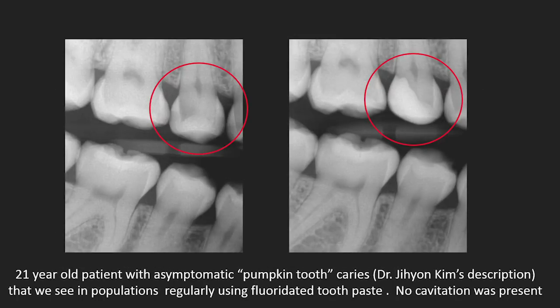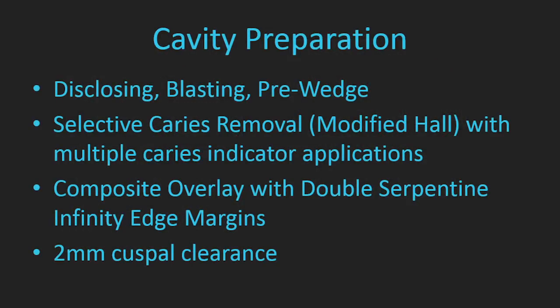So here's a deep caries case before and after. And you know, these new digital x-rays, I've talked to lots of clinicians about this. Sometimes when the decay gets deep, you kind of lose the clarity. So this is a lot deeper than it looks. And so once we get into this case, this decay is basically about 1 millimeter from bone level. So there's the pre and post-operative radiographs of the case with the compression joint, no mechanical retention. So let's talk about how we got this result. So first thing we're going to do is we always disclose and blast, and then we do selective caries removal.